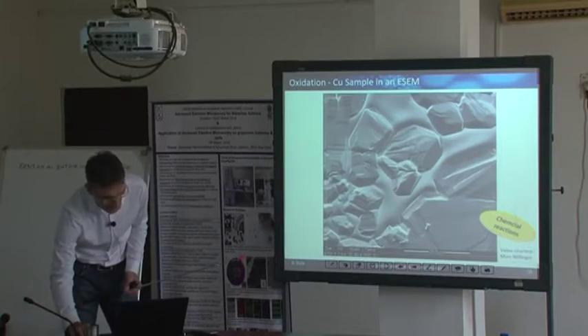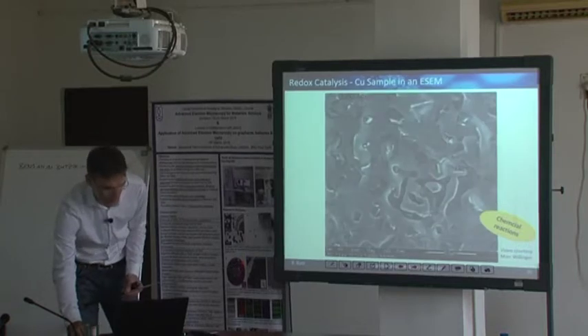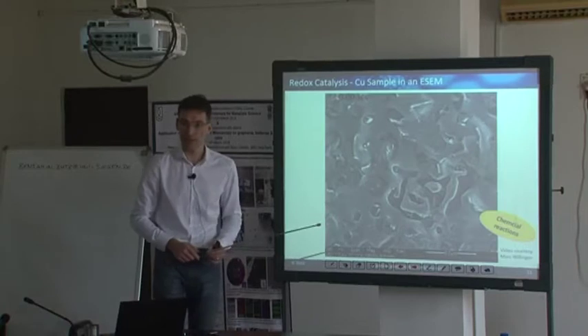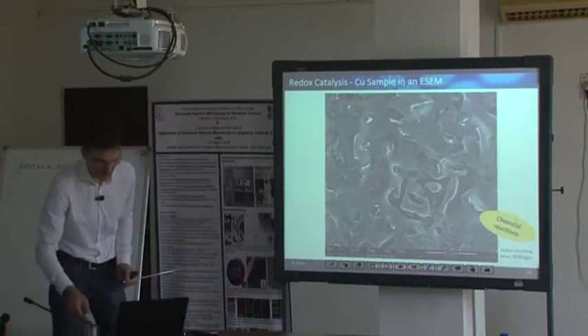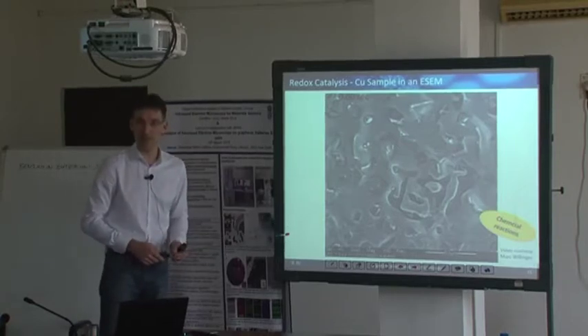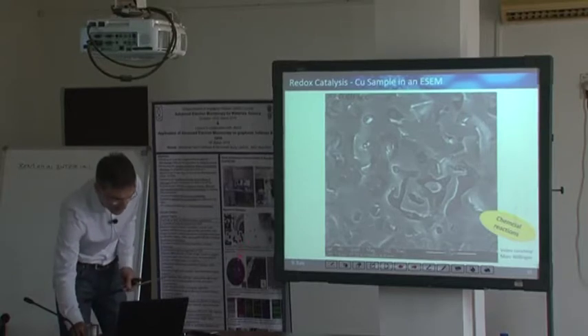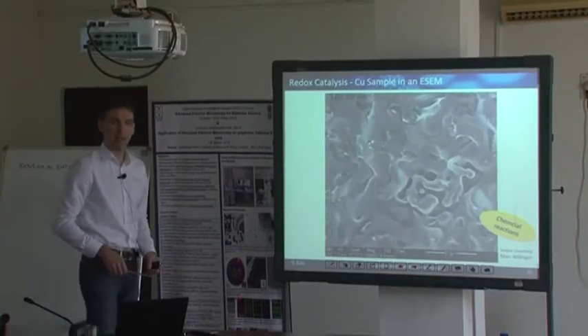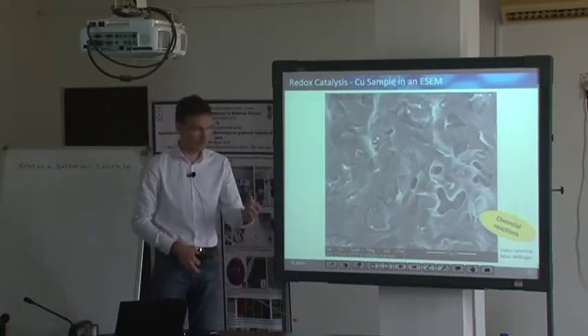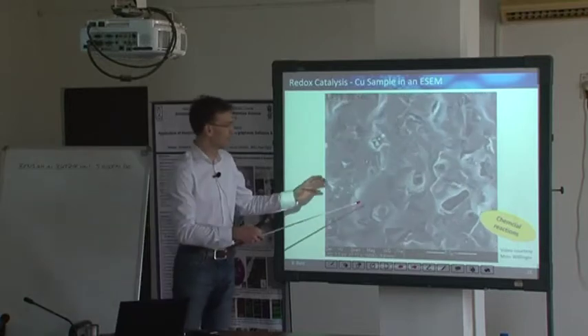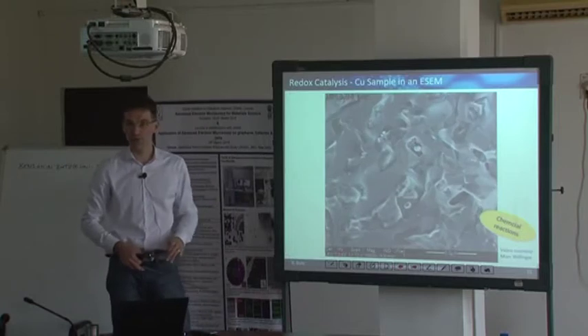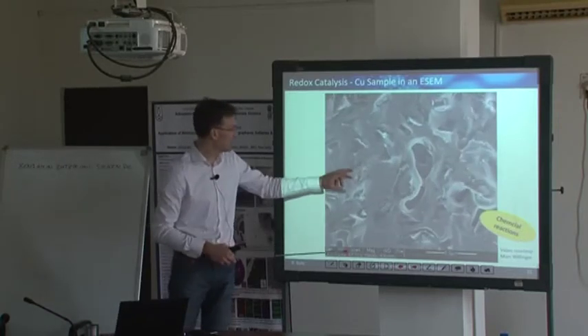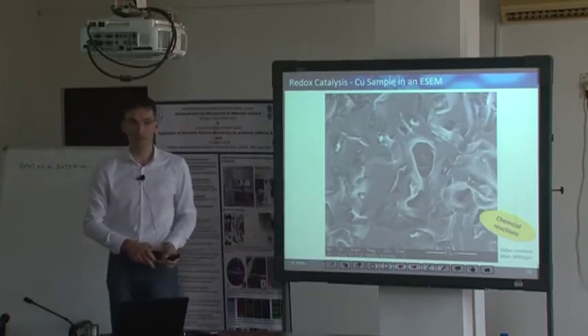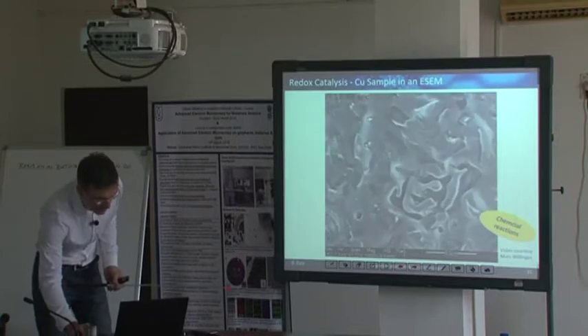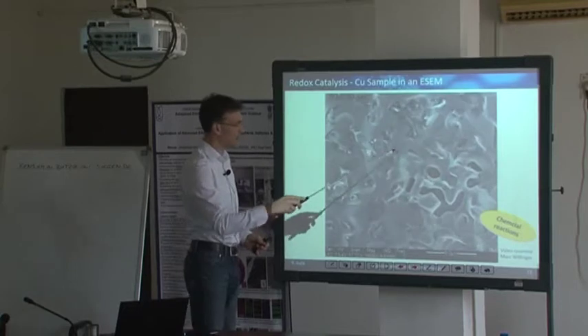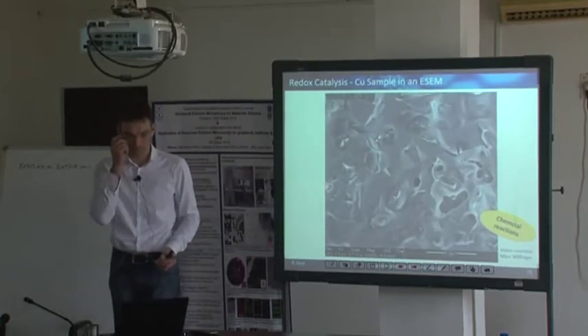And the same material under reaction conditions in a redox reaction. In this particular case, hydrogen and oxygen are introduced, whereas in the former case it was only oxygen at these temperatures. This is now a chemical reaction because copper is catalytically active, and this is how such a catalytically active surface might behave. It's not that you have oxidation and reduction on the atomic scale. This is a pretty severe change of the morphology of the whole surface during such a reaction. You see some areas which get oxidized, some areas which get reduced, and this is an interplay between local oxidation and reduction of such a catalytically active surface on a larger scale.